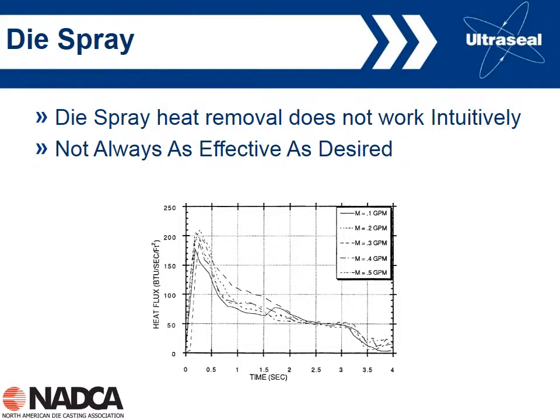So this is data that I showed in the first webinar, looking at the effect of spray on heat removal. As we talked about, the amount of heat removal is not intuitive in terms of how it works. It doesn't necessarily act as we think. We can't just keep on increasing the amount of spray and expect to keep on getting additional cooling of the die. So this is experimental work in terms of the amount of heat flux, i.e. the amount of heat extracted with time, for different spray rates from 0.1 gallons per minute to 0.5 gallons per minute.